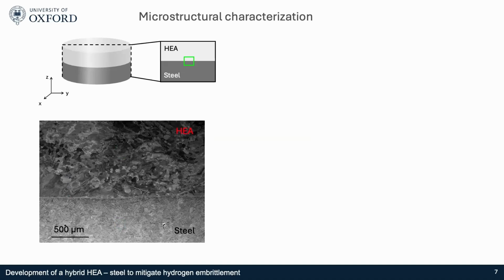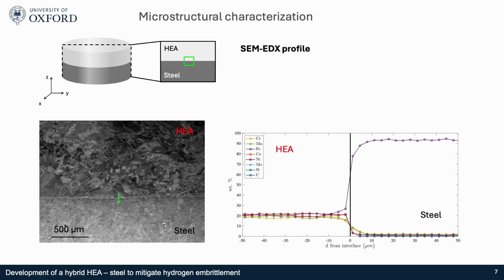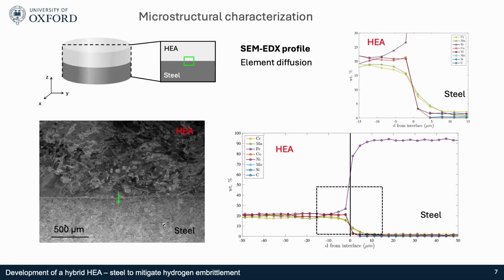Then, to see the transition of the chemical composition across the interface, we performed an EDX profile, and we can see here the equiatomic chemical composition of the high entropy alloy. Then, when we reach the interface, we have a sudden increase of iron and a decrease of the other elements that is more progressive. If we look in more detail at this interface, we can see that there is a region with element diffusion of around 10 microns. So we can say that the interface is like a transition zone between the two materials.